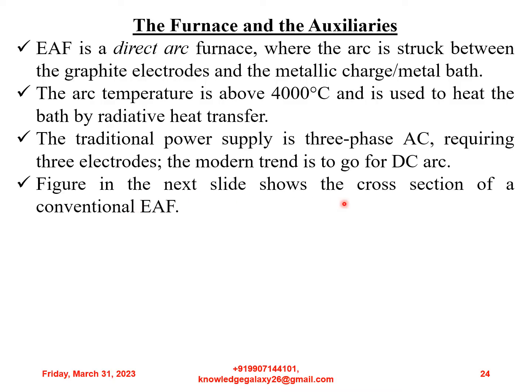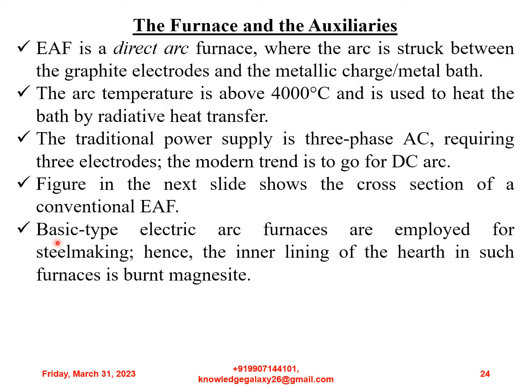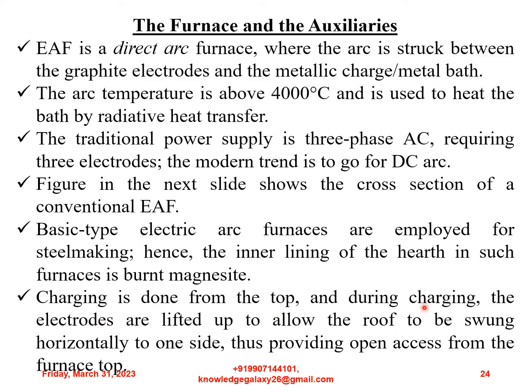The figure in the next slide shows the cross section of a conventional EAF. So in the next slide, the figure depicts the typical cross section of a conventional electric arc furnace. So you can observe that picture. Basic type electric arc furnaces are employed for steel making. Hence the inner lining of the hearth in such furnaces is burnt magnesite. Charging is done from the top, and during charging the electrodes are lifted up to allow the roof to be swung horizontally to one side, thus providing open access from the furnace top.